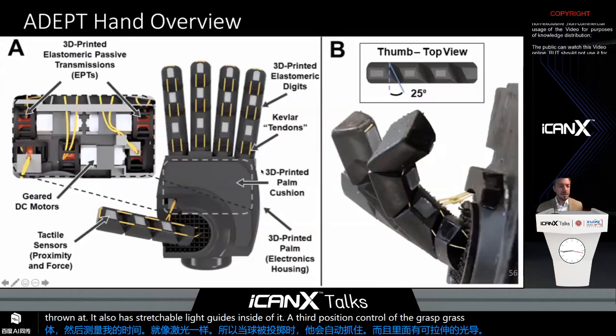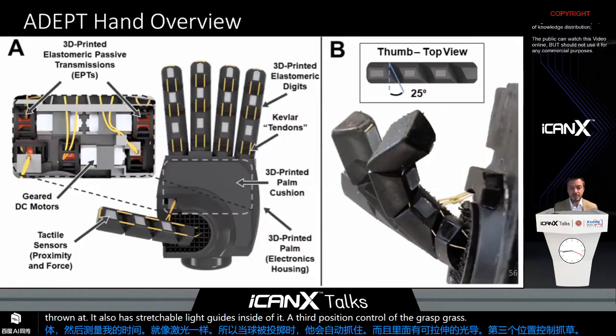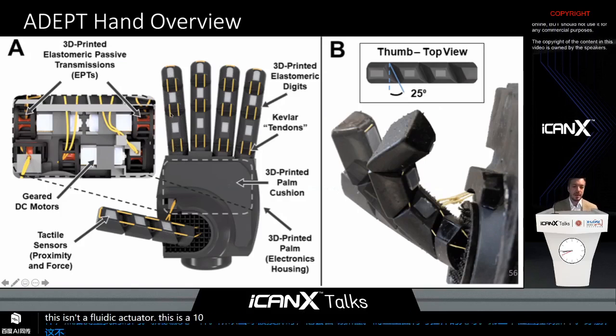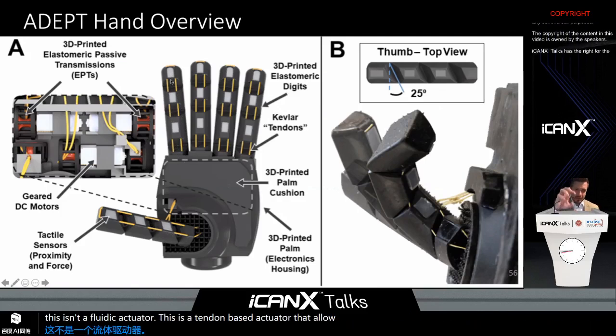Because this is 3D printed, we have exquisite control over the architecture and can put these small DC microgear motors, one per finger and two per thumb, on the inside of the palm of this hand, along with these gradient stiffness structures that allow rotation of the thumb, and the threading of tendons. This isn't a fluidic actuator, this is a tendon-based actuator that allows pulling and then grasping with the hand.